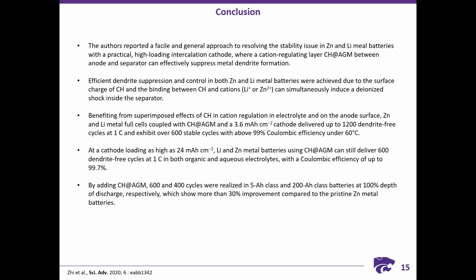Yeah, because AGM itself is quite thick, and essentially they have used 2 layers of separator. In the control experiments where they don't use the CH AGM interlayer, they have actually used 2 layers of AGM separator so that the thickness of the cell is consistent between the control and the experimental one. And the electrolyte amount has also been controlled, based on the cathode capacity. So the control cells and the ones with the interlayer are consistent in thickness as well as amount of electrolyte, but it does decrease the energy density because of the very high thickness as well as the amount of electrolyte, which needs to be worked upon.